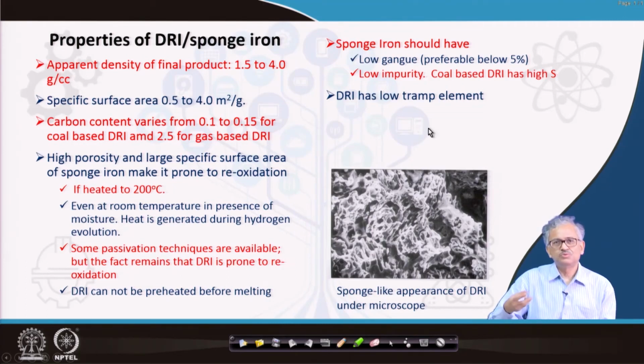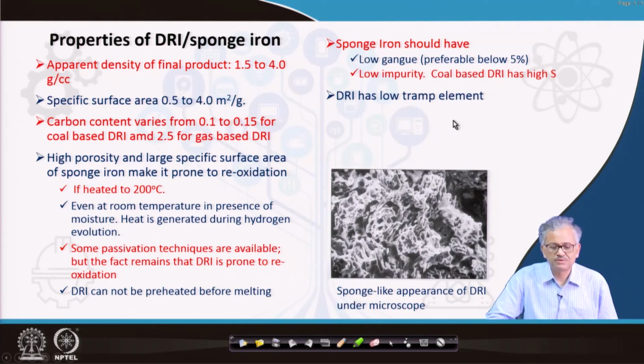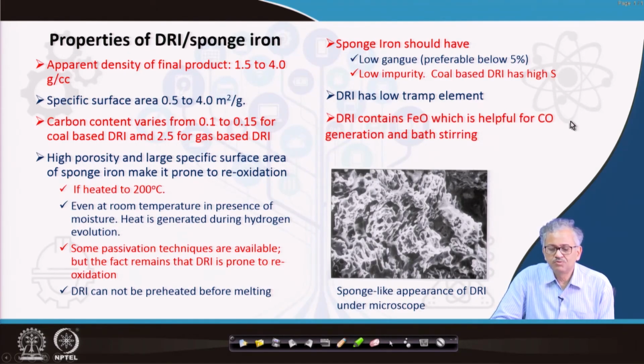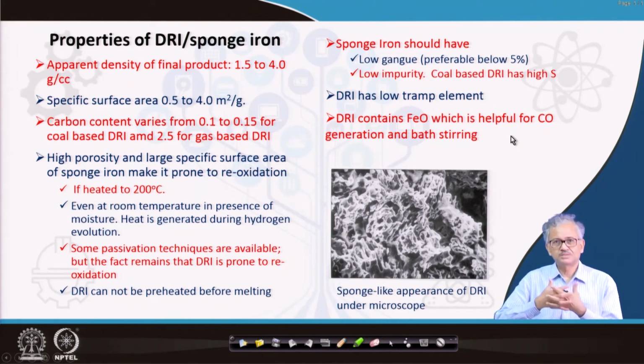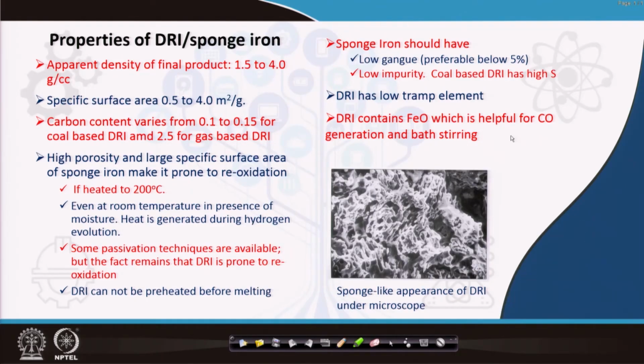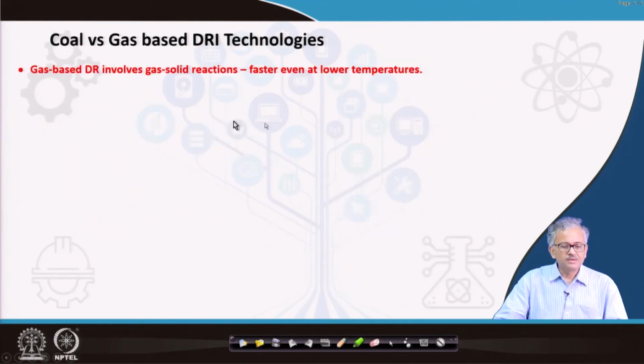The advantage of DRI is that it has low tramp elements, because scrap has a lot of tramp elements. The scrap is generated from different alloy steels, so it may contain molybdenum, nickel, chromium, and some other elements. So, a lot of tramp elements are there, but DRI does not have them, and sometimes removing these tramp elements is very difficult. DRI also contains FeO, which is helpful for CO generation and bath stirring, because even in 90% metallization some amount of FeO is there. But FeO should not be very high. Some amount is good.